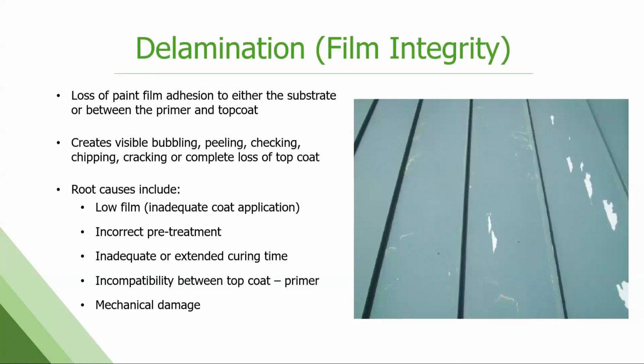Delamination or lack of film integrity. This is a tough one. These are the hardest warranty claims that we deal with because you just don't always know the root cause. Usually it happens after the product's been installed for a long period of time. It can present as just the top coat coming off the primer. It can present as the whole paint system coming off the metal. It can be bubbling, peeling, chipping, cracking. There's a lot of different ways it presents. There's actually about 500 root causes for it.